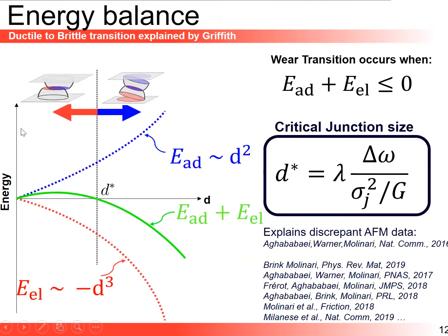Okay, so looking at the energy map as a function of D, D is the size of a junction. So it's a geometry. It depends on your roughness, on the type of asperities you imprint on the material. So you store the elastic energy. Remember, it depends on D cube. So when D is small, this is a negligible quantity. So elastic energy is money you have at the bank, and you can use it to buy yourself the blue curve, adhesive energy that grows with D squared. If I sum those two quantities, I get the green curve. And you see this green curve is initially positive, then it becomes negative at the critical length scale D star. Below D star, you don't have enough elastic energy to create cracks, and therefore you will flow plastically.